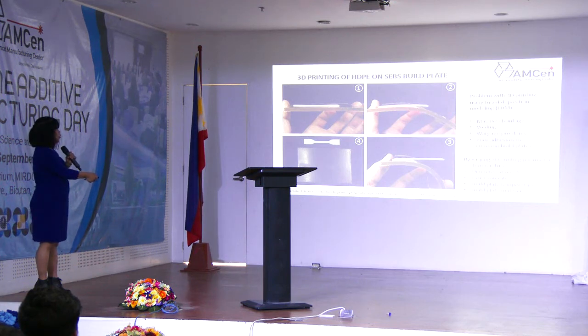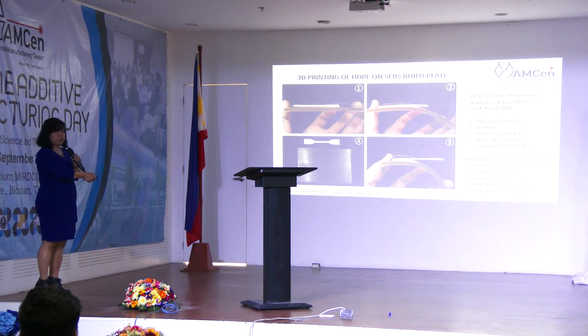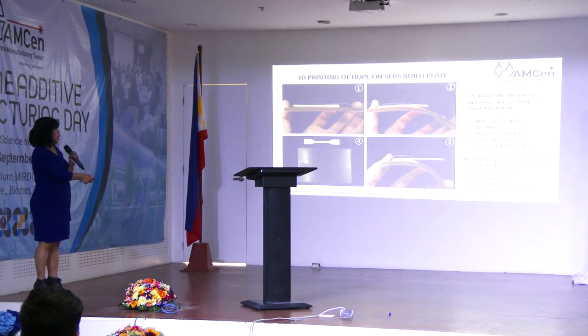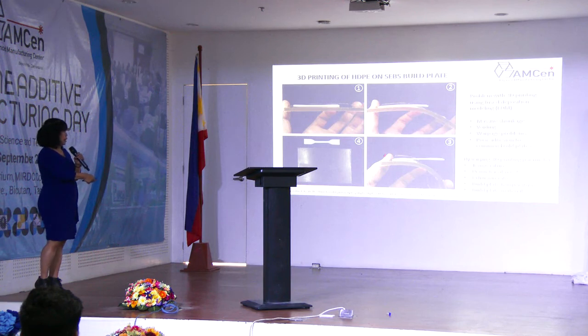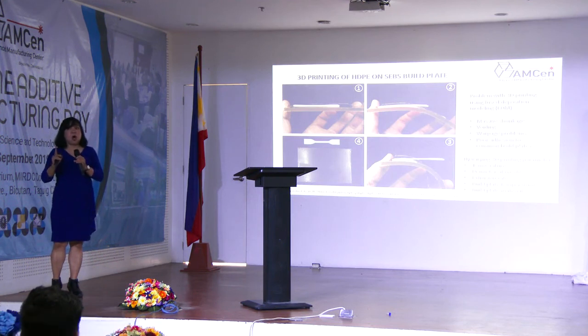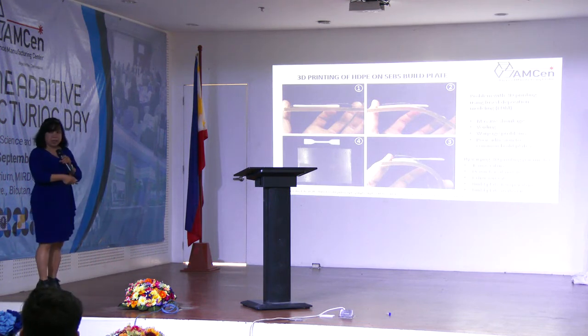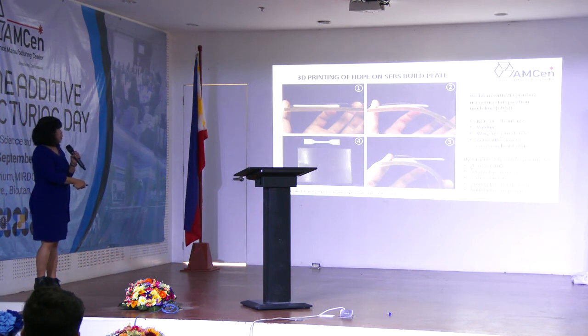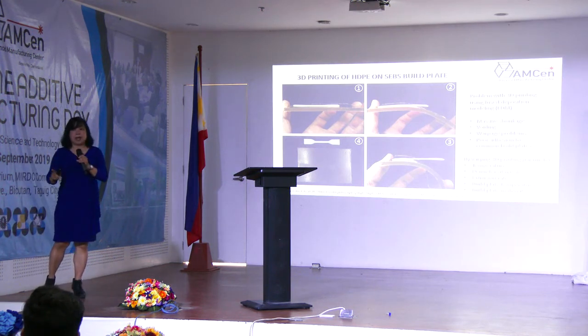So as I had mentioned before, the reason why we didn't get a good print is because the material has a massive shrinkage, right? Which caused voiding, warpage, and poor adhesion on the build plate. But before you can get good results, mind you, you still have to optimize the 3D printing parameters such as the temperature, the diameter of the nozzle, the extrusion rate, the build plate temperature, and getting the right build plate material.